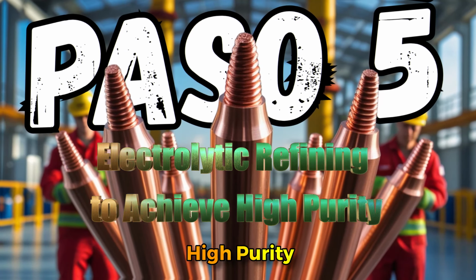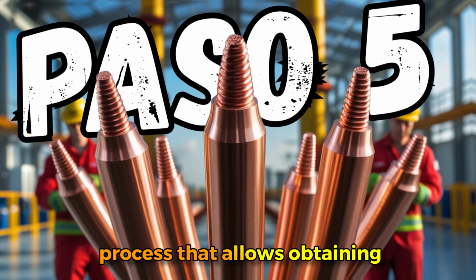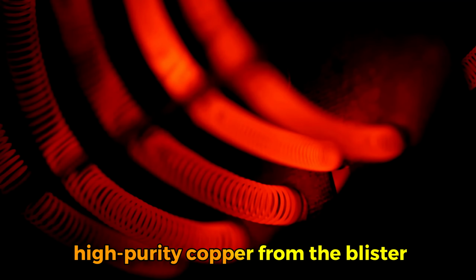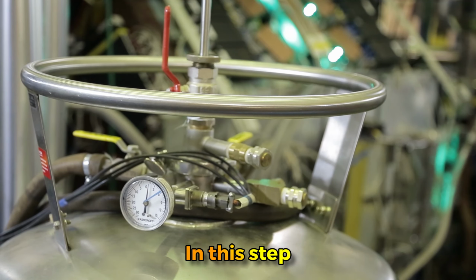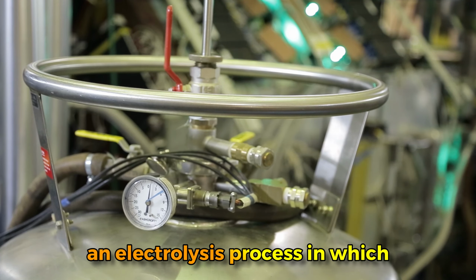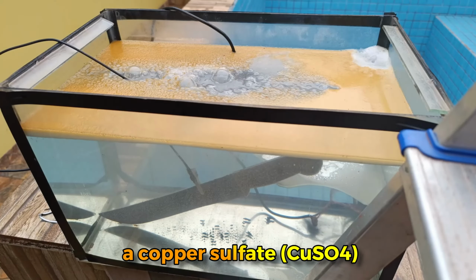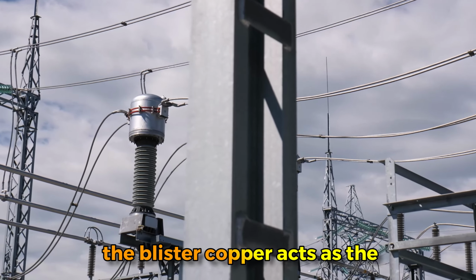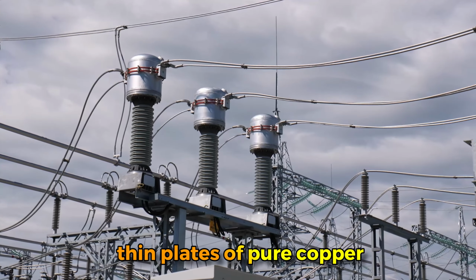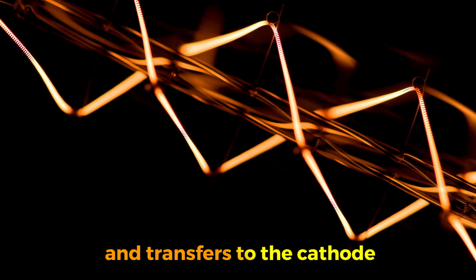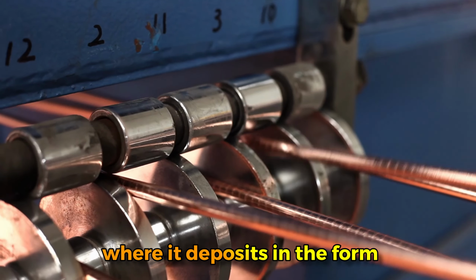Step 5. Electrolytic refining to achieve high purity. Electrolytic refining is the crucial process that allows obtaining high-purity copper from the blister copper obtained in smelting. In this step, the blister copper undergoes an electrolysis process in which a copper sulfate, CuSO4, bath is used as an electrolytic solution. This process is carried out in an electrochemical cell consisting of copper electrodes. In the cell, the blister copper acts as the anode, while the cathodes are made of thin plates of pure copper. When electric current is applied, the copper from the anode dissolves and transfers to the cathode, where it deposits in the form of pure copper.